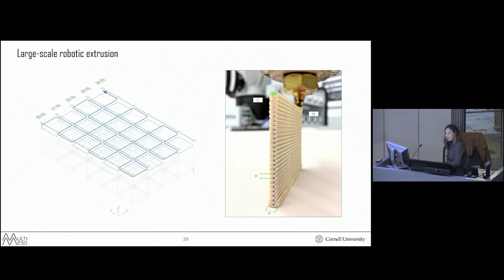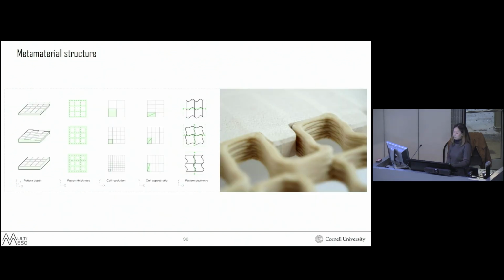Now, in transitioning from the small-scale 3D printing to the large-scale robot extrusion, it was necessary to make some adjustments in the extrusion toolpaths, which had to be continuous and non-crossing, due to the larger nozzle and delay caused by pressure buildup inside the barrel. So there's a lot that we can do at the small scale that we can't do at the large scale. I also had to recalibrate the 3D printing parameters, although the general relationships between depth, thickness, resolution, aspect ratio, and geometry remained the same.